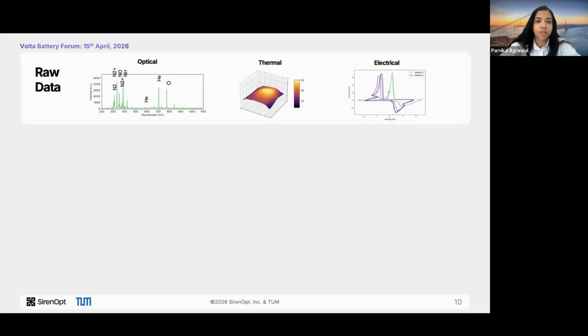So now that we have this really rich raw data, we collect close to 200,000 raw data numbers per measurement location, as I said. And on any given sample, you will have several hundreds of thousands of locations, depending on how fast or how comprehensive you want to be in your scan. Let's just focus on one specific location. What do we do with that data? This data is then in Plasma Smart, which is our decision-making software. We extract 9,000 physics-based features out of this raw data. As I said, this raw data represents 200,000 raw data elements per measurement point, which are then extracted into 9,000 physics-based features. These are features like the ratio of peak intensities in the OES, or the mean temperature or temperature variance in the thermal image, or the current RMS value in the electrical signature.